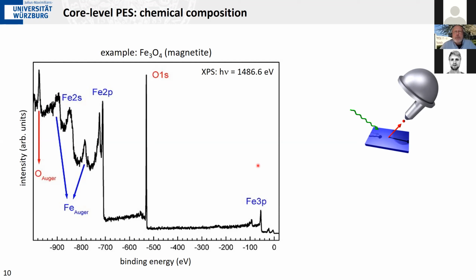A second feature that I would want to point out here, and we will address this a little later, is that as you go to higher and higher binding energy, you see a smooth, unstructured background that is increasing monotonically as you go to higher binding energies or lower kinetic energies of the photoelectrons. And these are due to secondary electrons that are generated by inelastic collision processes that occur when photoelectrons transfer from their locus of excitation to the surface before they are released into the vacuum.